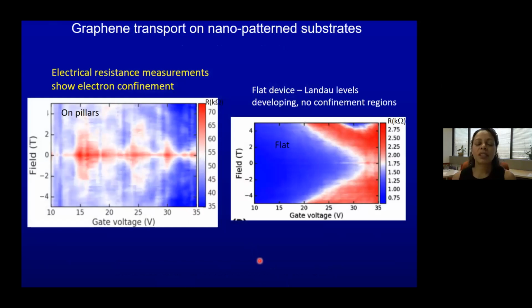Okay, so now we know it's strained, but one of our goals is also to look at transport, right? So we want to see how the transport differs on flat versus this strained patterned graphene. And so these are conductance measurements. This is a 2D plot where the red lines show you the highest resistance and the blue is the lowest resistance as a function of field and gate.